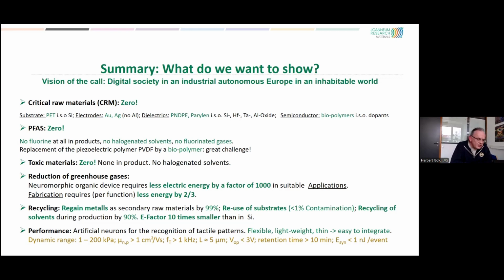When it comes to performance, these soft performance parameters are good. So it's flexible, lightweight, thin, and therefore it's easy to integrate, even in the human body. These are the pluses, but on the downside we have a mobility of 1 square centimeter over volt seconds and frequencies in the kilohertz range and channel length of 5 microns. So if a silicon manufacturer sees this, he would say this is poor, but as we said, in these edge computing applications, the integrability would weigh more than the performance in terms of speed.